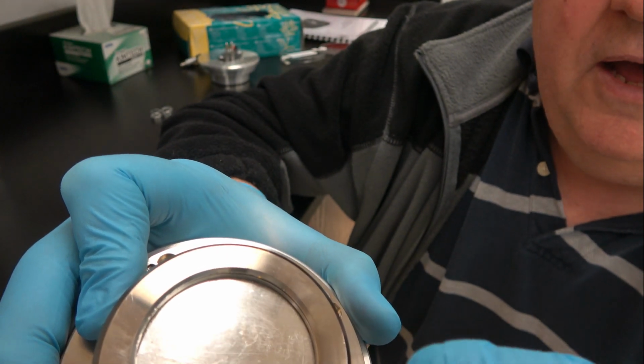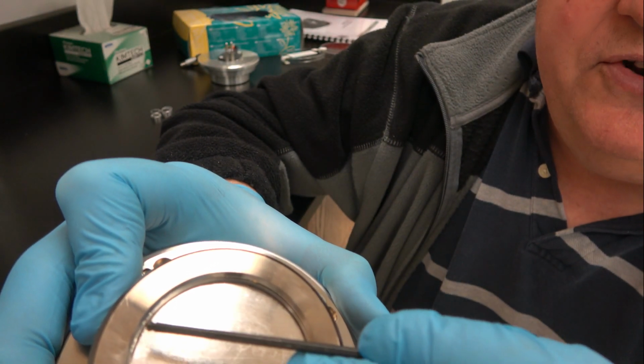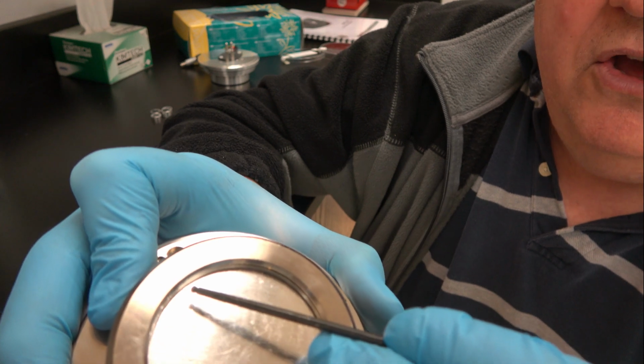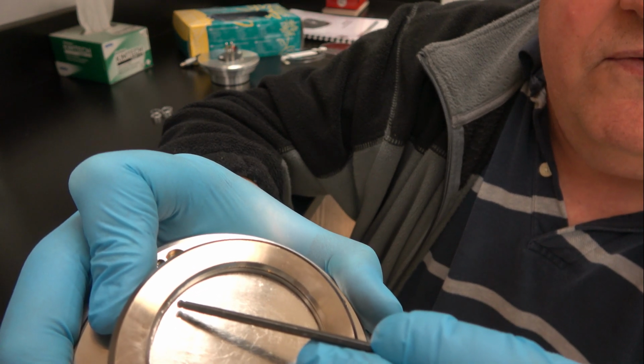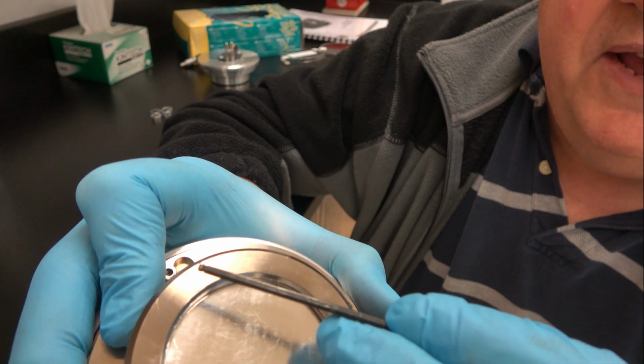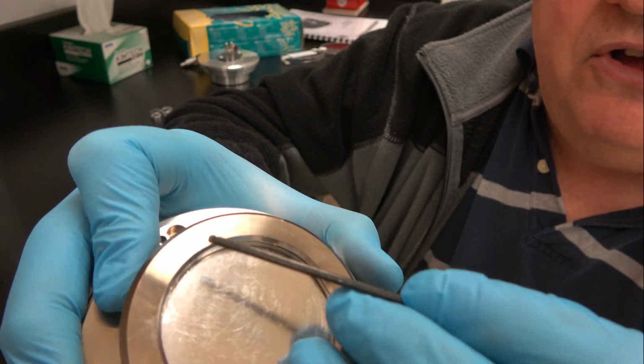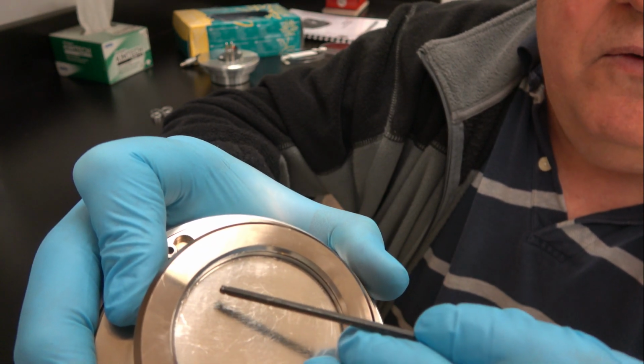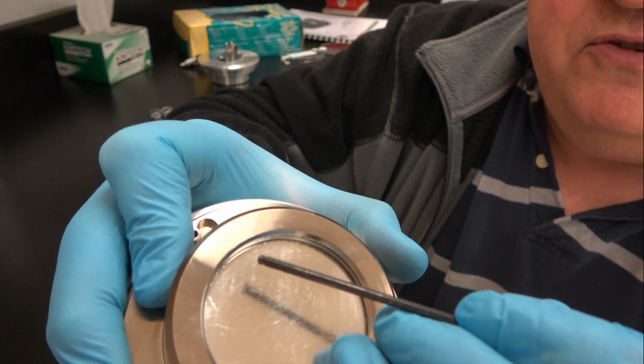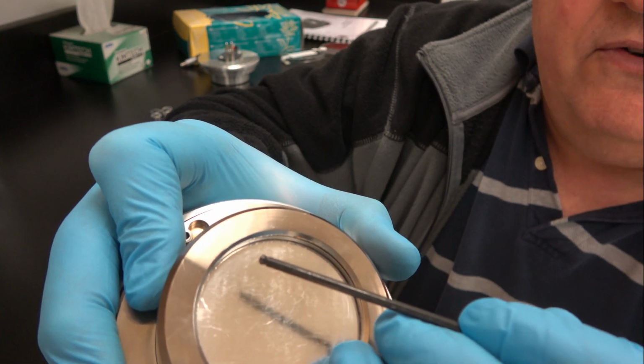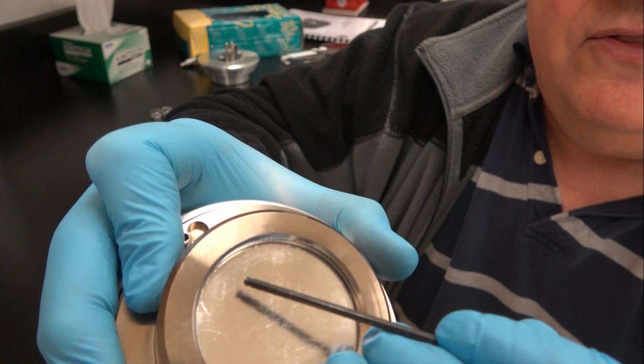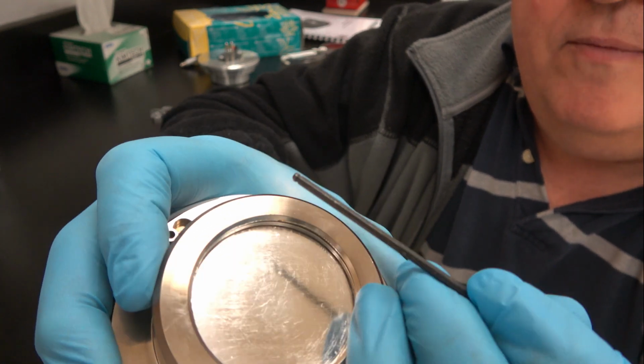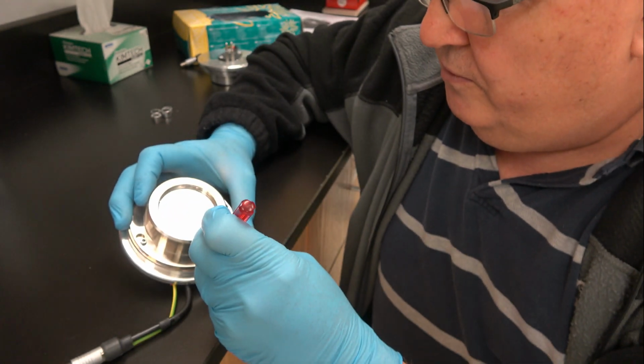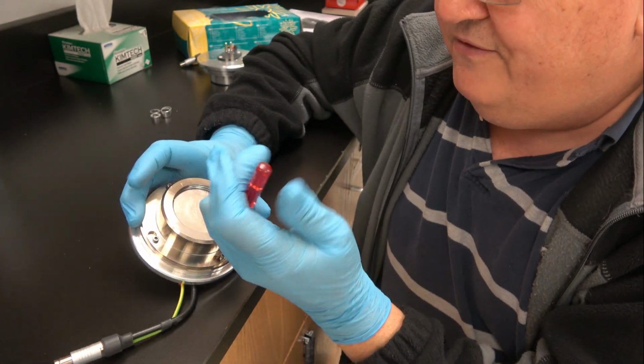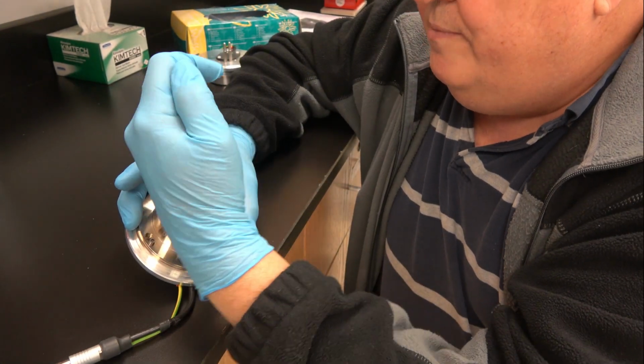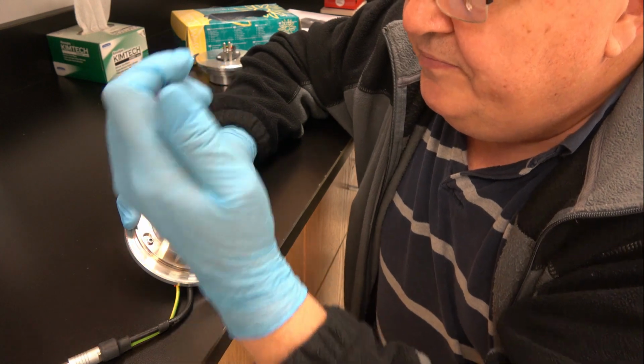So what happens is you get a short. A piece of this metal will flake off and go from the dark space ring, which is at ground potential, to the target, which is at some high voltage potential between 300 and 600 volts. So this shorts out the power supply and gives you the error message. So the way you remedy it, the first step is to remove the dark space ring.